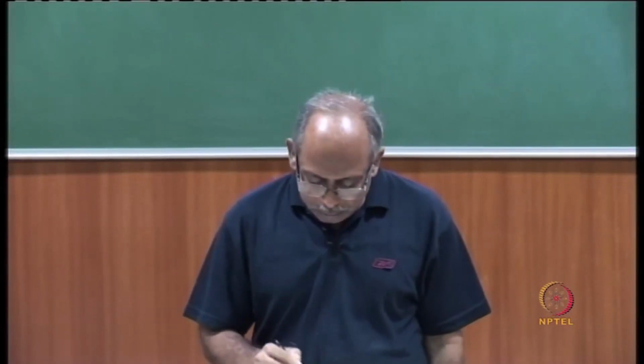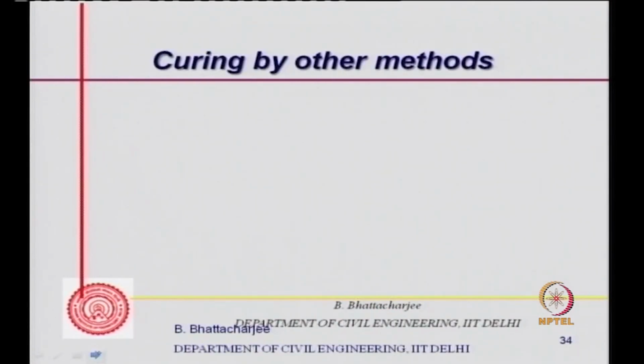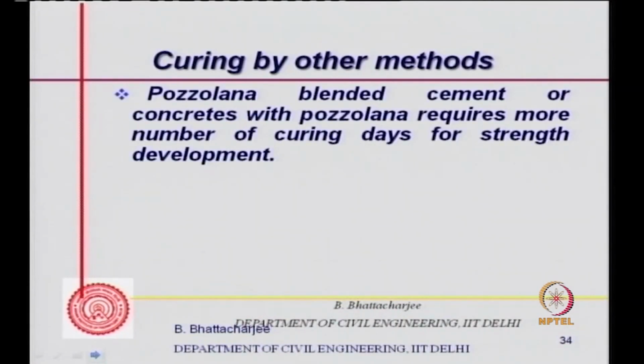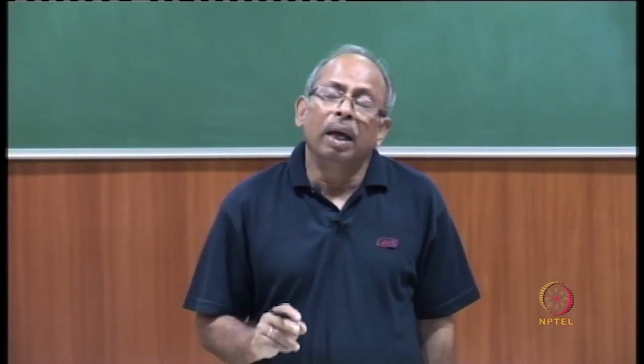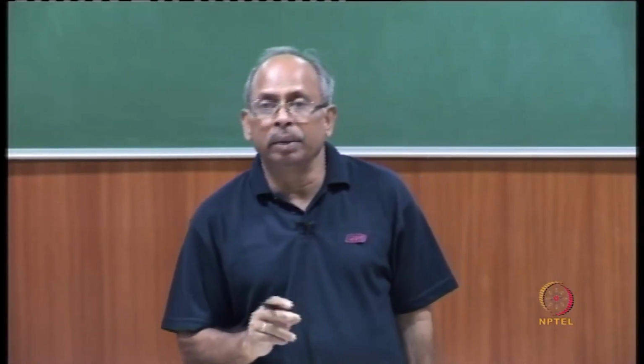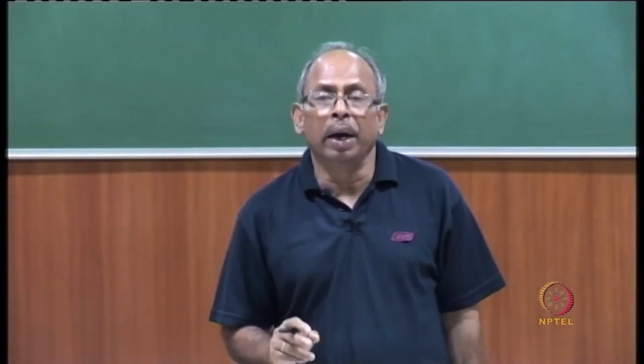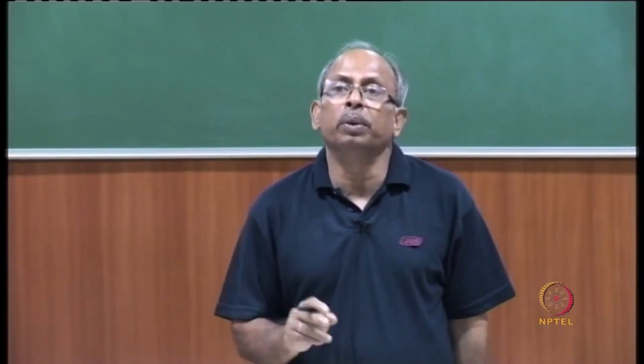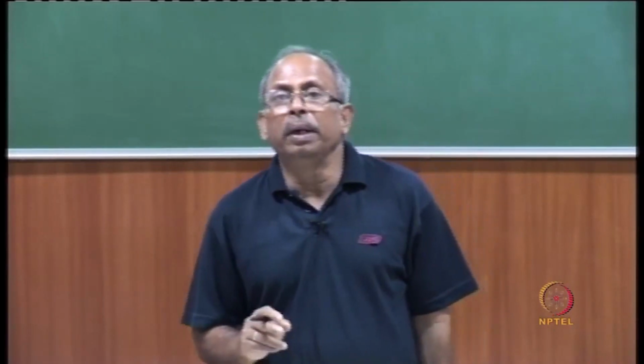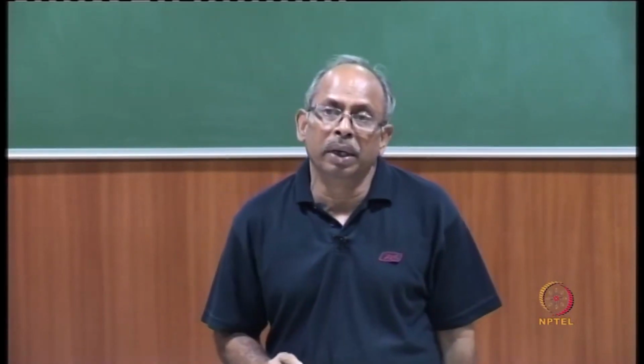So codes actually specify minimum curing days based on this. For example, the Indian code says that 7 days minimum curing is required for ordinary Portland cement, but if it is pozzolana blended, then you will need 10 days in normal weather, and 14 days in dry weather like desert areas where it is more dry. Pozzolana blended cement requires more curing days for strength development, because that process is slow.